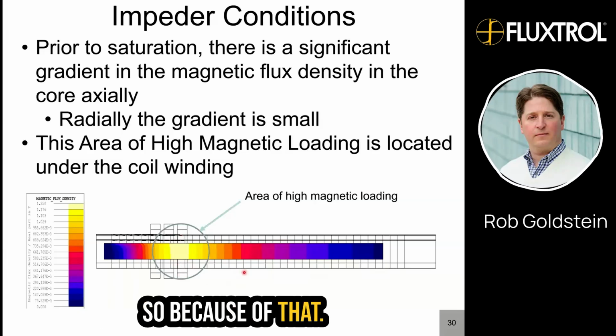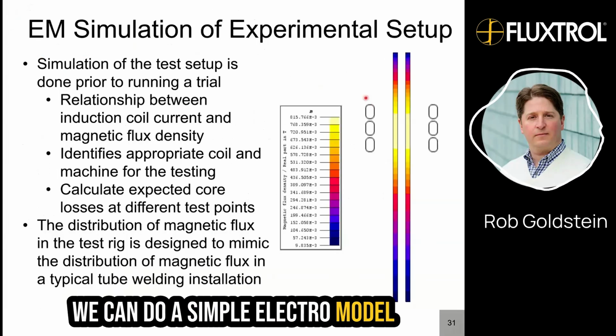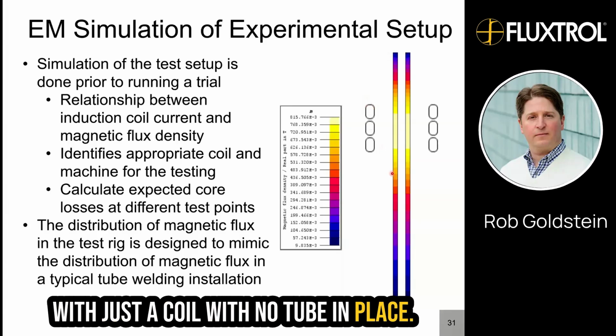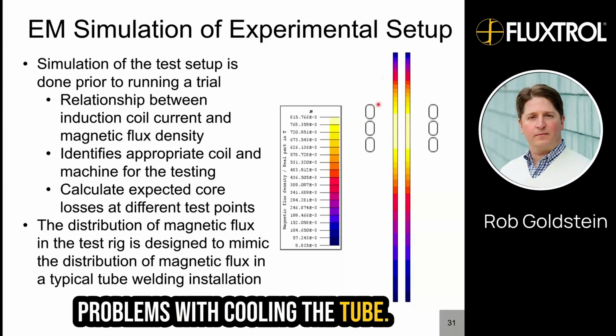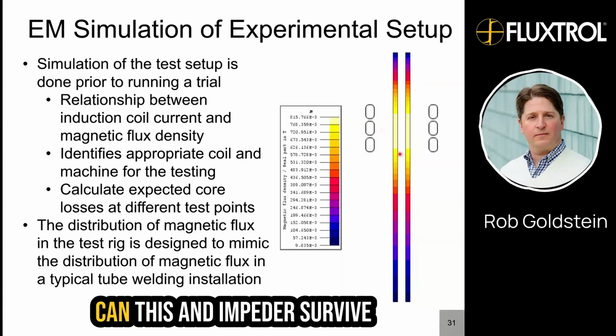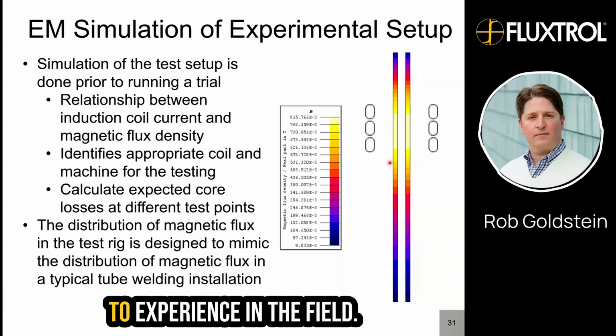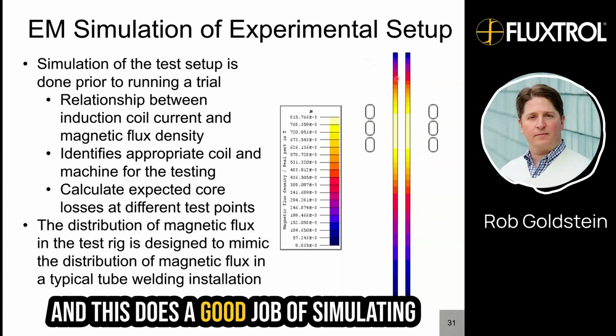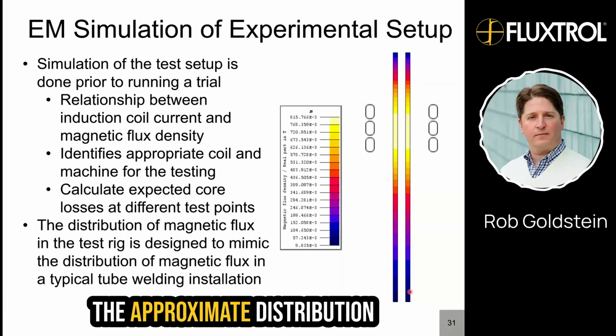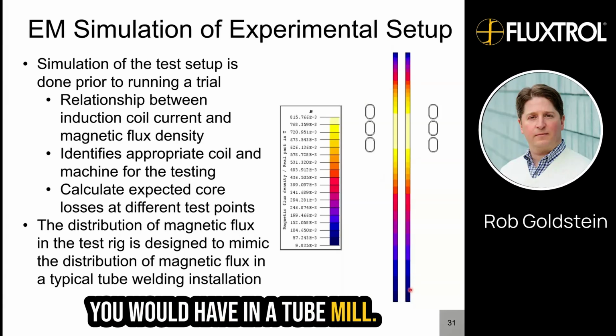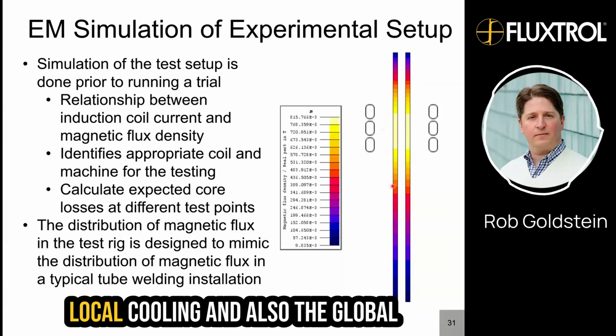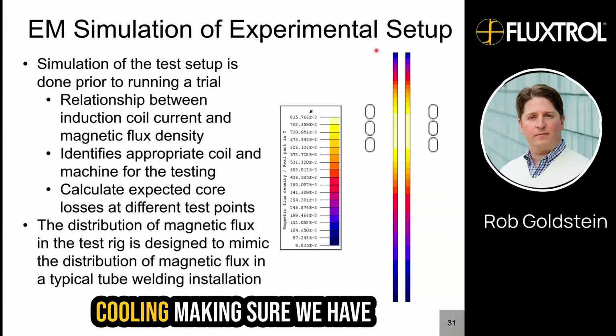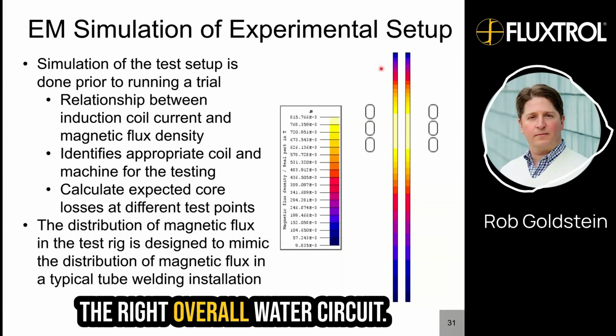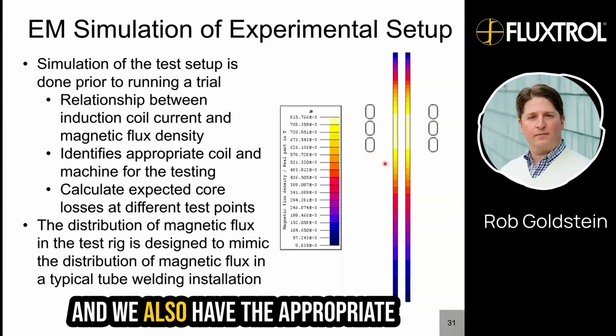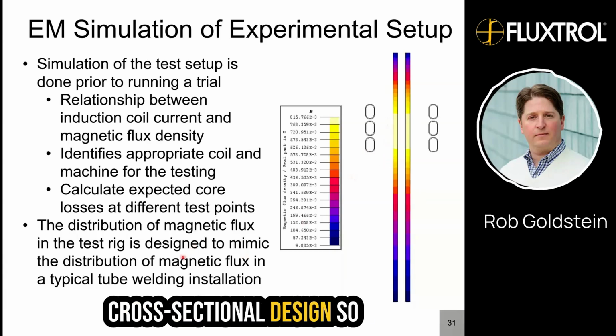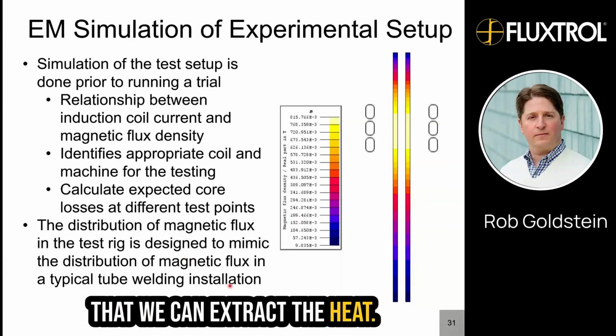Because of that, we can do a simple electromagnetic model with just a coil with no tube in place. Otherwise, you have all the problems with cooling the tube. So we're focused really on, okay, can this impeder survive in the conditions it's going to experience in the field? And this does a good job of simulating the approximate distribution you would have in a tube mill, and verifying that we can do this local cooling and also the global cooling, making sure we have the right overall water circuit, and we also have the appropriate cross-sectional design so that we can extract the heat.